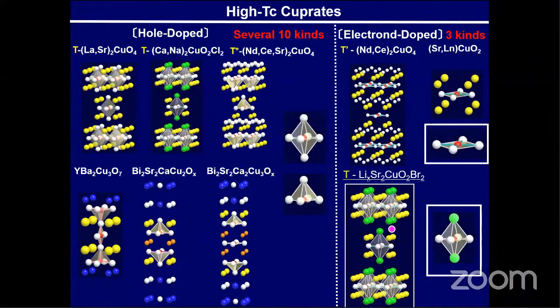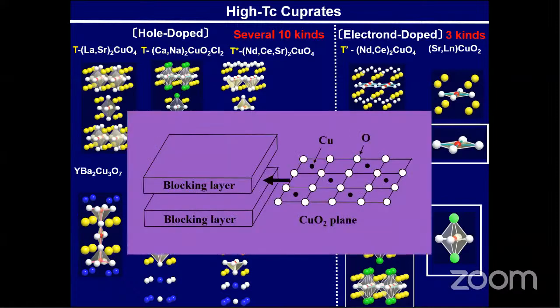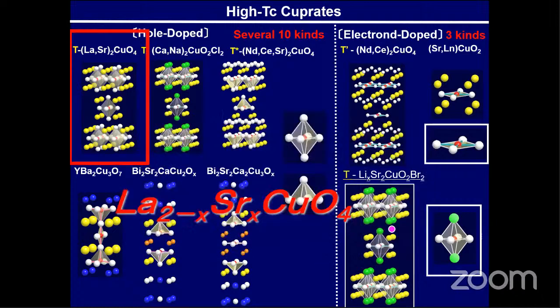So then what is the typical property of the high TC superconductor? This is its structure. This is the typical structure of the high TC cuprates. This seems to be like a low dimensional structure. It's like a blocking layer inserted by the copper oxide plane layer. Then this is a basic mechanism. So the supercurrent in the superconducting state is passing through these copper oxide planes. This is a common property of all of the high TC cuprates. Then this is La2-xSrxCuO4, the lanthanum strontium copper oxide.